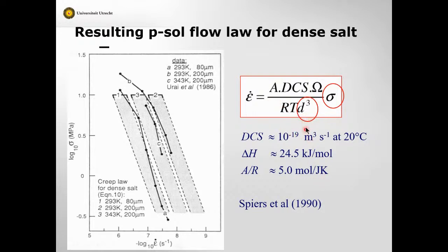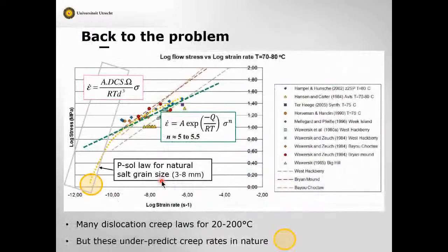But of course, the key thing here is, look, this was all very fine salt. We could see creep by this mechanism at lab strain rates around 10 to the minus 8, for 0.2 of a millimeter grain size salt. So if you go to 2 millimeters, it's already 1,000 times slower. So you can immediately see, to measure this process in a lab experiment on natural salt with a grain size of several millimeters is not going to be possible, or is going to stretch the absolute limits of time.